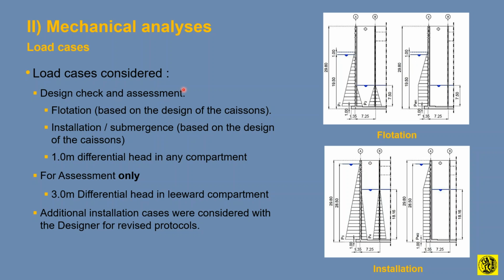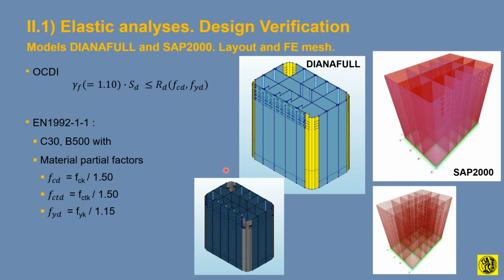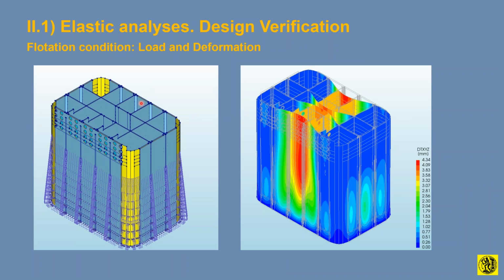Now, for the flotation, the design check and assessment, we checked both of these and the 1 meter design code specification using elastic analysis. And then for assessment, we did all of these plus the differential that showed the picture during the collapse, the implosion of the caisson. Now, okay, the elastic analysis, the original design was done by another program by the designer. So we actually ran the same problem twice, once using Diana and once using this guy here, with the same load conditions and everything, linear elastic. And these are the results of the elastic analysis for the flotation condition.